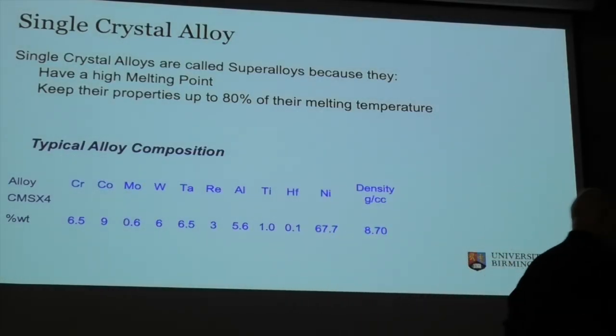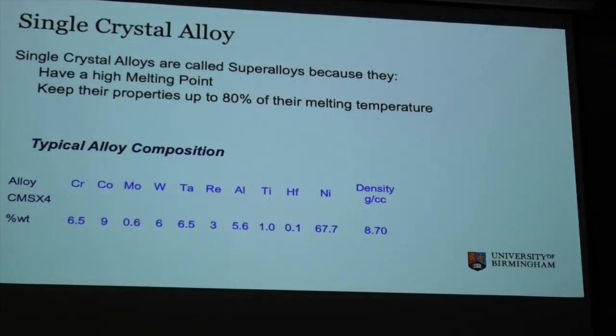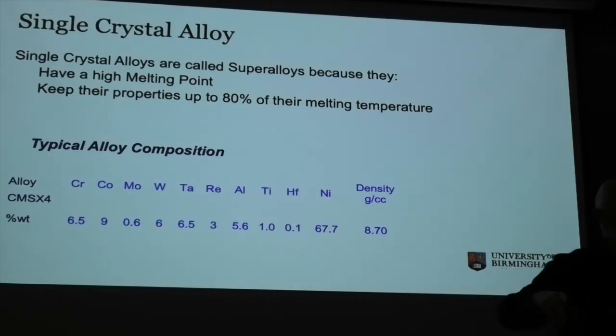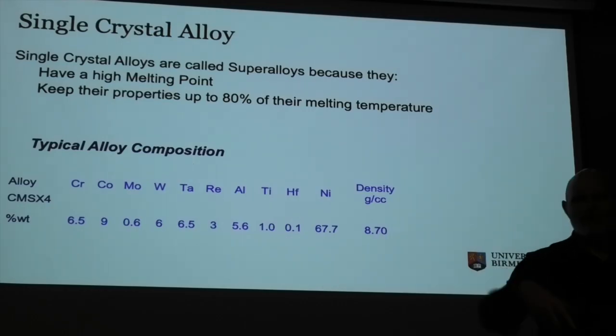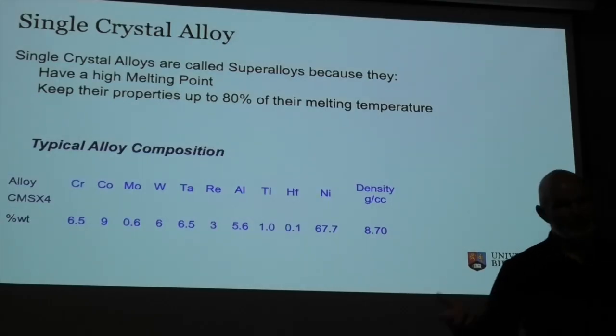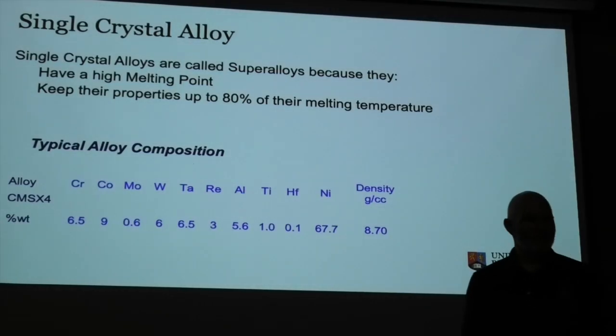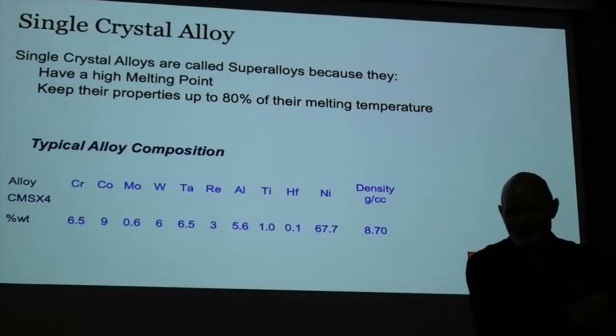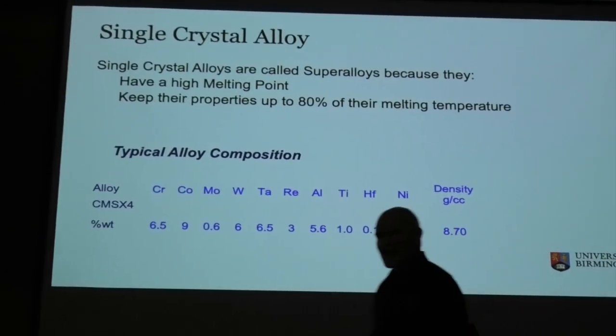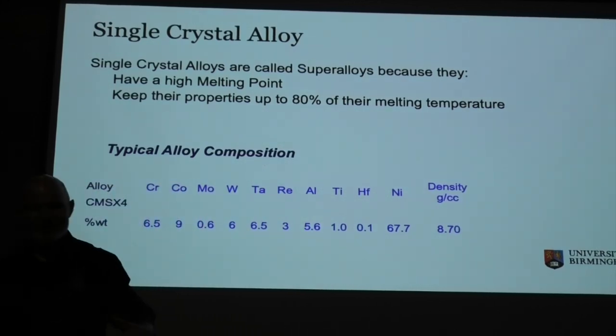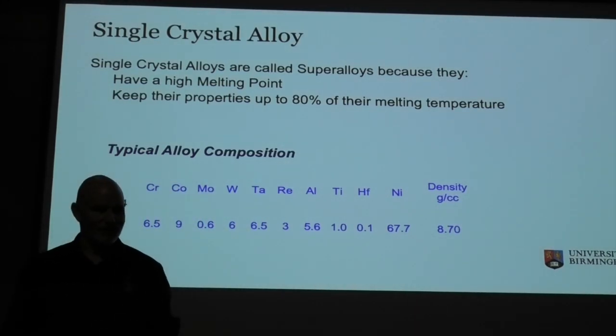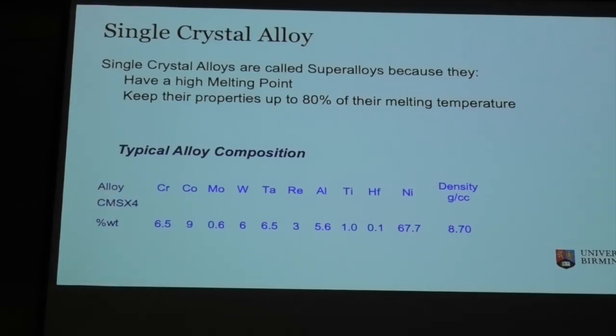So we have thrown just about everything at it. That's mostly because every time we put something in, we find it's not so good long term. So we don't want a load of aluminium, so we replace aluminium with titanium and tantalum. But that gives us issues around castability, so to compensate for the issues we get, we chuck in something else. A bit of chrome goes in there for oxidation, because aluminium is really good for oxidation resistance, but we're taking it out, so slip in a bit of chrome. But that's not good for castability, so let's stick some cobalt in there to compensate. There's no element that's really, really good for everything, so we're always compensating for its deficiencies by chucking in something else, to the point where we've probably got to as far as we can.